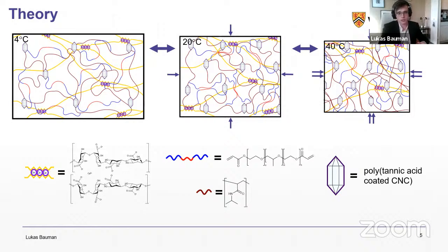So here we have a figure that shows the different states of the network at different temperatures. Initially it's fully swollen, and then at 20 degrees centigrade, we go above the LCST of the Pluronic P123, which is a block copolymer. So it's polyethylene glycol, polypropylene glycol, polyethylene glycol. And at this point, it starts having hydrophobic interactions and it pulls the network together. So you get deswelling above its LCST, but this is more of a step rather than a gradual deswelling.